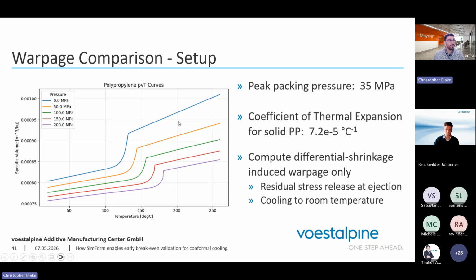On the topic of warpage, to compare the resulting part quality for the 2 cooling designs, we performed this warpage analysis, which takes into account warpage that is induced by differential shrinkage. So taking into account the main contributions of residual stress that is stored within the part just before it's released at ejection time, and then the free shrinkage as the part cools down to room temperature outside the mold.